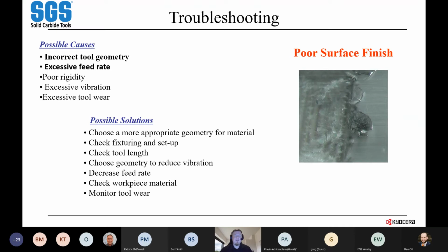And if it is, then you look at your fixturing and setup. Make sure you don't have too much tool sticking out. If it's not, then you can look at better geometry that's going to give you better shear, better engagement, whatever the case is, wherever you're having problems with that finish, in order to be able to improve it. Of course, lower your feed rate. Finishing rates should not be overly aggressive, because you want to give the tool a chance to work, and really cut with small movement in between one flute to the next to get that higher quality finish.